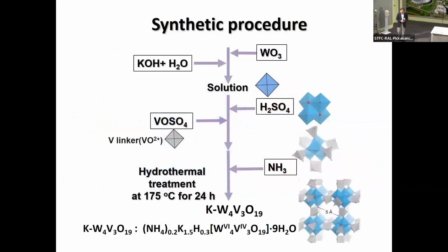The preparation process is quite simple, as you can see here. You just dissolve the tungsten oxide in a basic solution. Then you obtain monomeric tungsten oxyanion species in solution. Then you add sulfuric acid to get an acidic solution. Under the acidic conditions, monomeric octahedra aggregate to form Keggin species in the solution. Then we add vanadium sulfate, which is a cationic species. On the other hand, the Keggin unit is an anionic species. So the two species can react together to form this kind of species in solution.